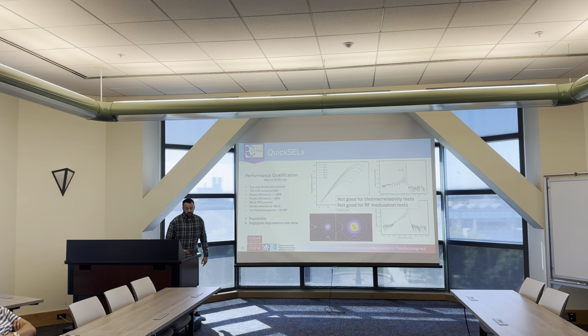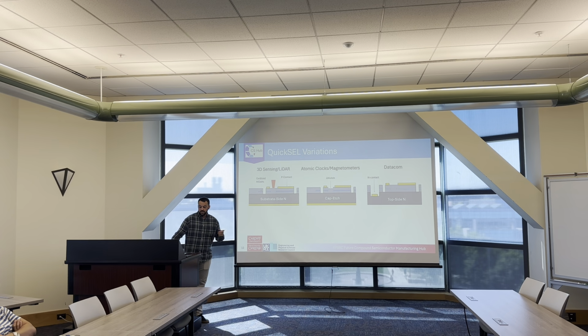So some things it can't do though, it's not good for a representative lifetime or reliability test, and the modulation response as well, it's not representative. So there's some variations: 940, 3D sensing LiDAR applications, that's our standard QuickSEL. And then sometimes developing EPIs for atomic clock magnetometer applications. So they can be grown with an anti-phase cap, so it requires an extra etch step, a quarter wavelength etch step, which I'll talk about a bit in the next slide.